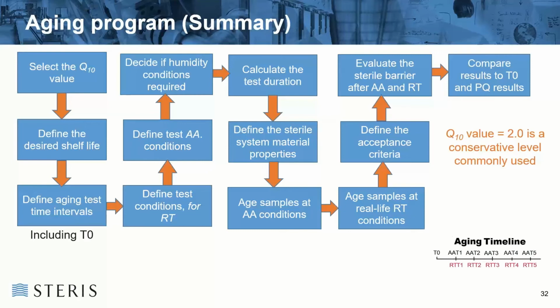There's no point in just doing, say, the likes of a peel test or a bubble leak test and not comparing it to anything. So what I suggest there then is that you compare your results back to both the T0 results and the PQ results from where you've created your seal in the first place, to see if there's any significant deviation or deterioration in the seal strength over that period of time while it's been in its aging, or during the real-time shelf life.